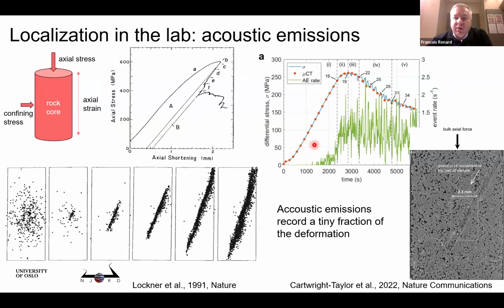So that's something we are working on. We look at how the localization occurs in this part of the curve. Yeah. Before it reaches the plateau and there is a weakening, because the weakening is really when there is almost a through-going shear zone. Yeah. And localizations in our case start here. Yeah. And we look, for example, at how the local dilation localizes, how the shear component of strain localizes, how the local compaction localizes. Mm-hmm. But even in this part of the curve, which looks linear,